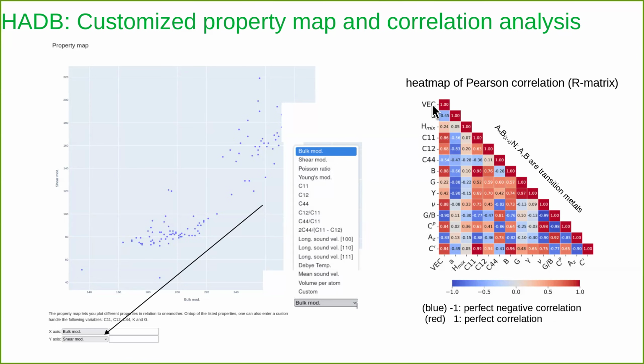So you can see how strongly the valence electron concentration is correlating with, let's say, the Poisson ratio or the Cauchy pressure and so forth. Or on the opposite way, we can see how the valence electron concentration is negatively correlated with G over B, so the shear modulus versus the bulk modulus ratio. So that gives really a lot of new information for industry to select the right material.